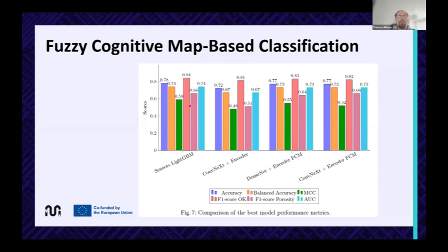So here we have all results combined for different types of models. And here we have only the best results. So we can see that different measurements, different metrics have different values. So for images, we have a bit lower MCC in comparison to light GBM, but it must be stated that not the same results were obtained during the tests by the light GBM, using these average values, and by the thermal images. So then they can be just used together to overcome problems from one or other classifier.